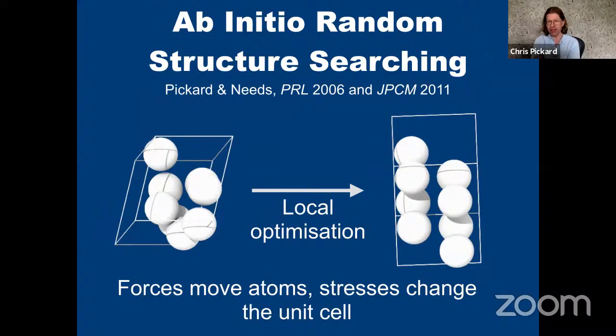So my method is known as ab initio random structure searching. I introduced it in 2006 and wrote a longer paper about it in 2011. And the idea is simple. You start with an initially random structure, and then you locally optimize, you move the atoms downhill until they won't move anymore. That is in terms of the forces for moving the atoms through the unit cell, and then the stresses which change the shape of the unit cell. Now, if you do this once, odds are you won't get a very nice structure.